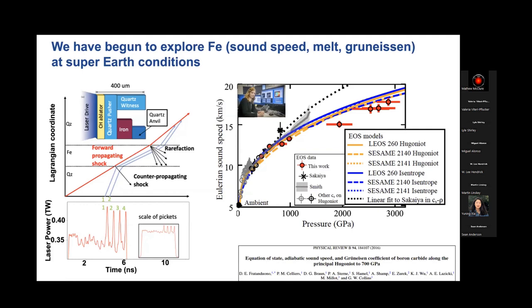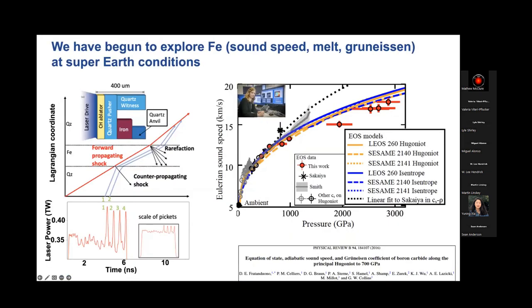So let's see, I'll just quickly run through this. Maggie has been looking at the properties of iron, the deep interior states, the solid and liquid state. She did these really elegant experiments where she launched a shock wave and then she threw in a series of pickets, followed those pickets as they moved through the iron, and that allowed her to map the sound speed as well as the Gruneisen parameter and also get the melting temperature. And what she found is that the sound speed is quite a bit lower, so that already tells us how we can interpret a lot of seismic data.